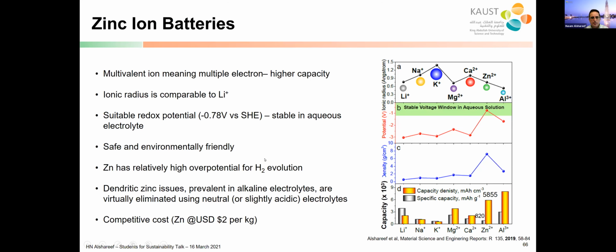One of the batteries we have been working on is zinc-ion batteries. And zinc has a lot of advantages. The oxidation state of zinc is higher than lithium, but its radius is similar, although when it's surrounded by the solvent, this may change. Its redox potential compared to the standard hydrogen electrode is only minus 0.7 V compared to the others. So there's less chance of this water splitting issue. It's safe and environmentally friendly. And it has issues like dendritic growth that we have to work on, but its cost is also competitive.